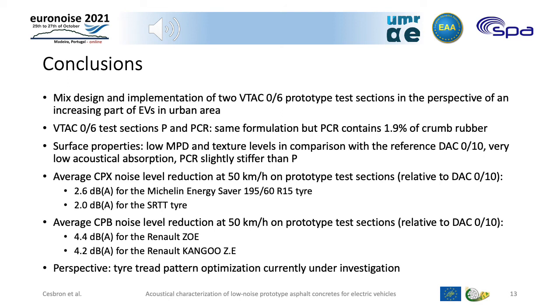A very low acoustical absorption was measured on both prototype test sections. Regarding the mechanical impedance, the PCR test section was slightly stiffer than the test section P. In terms of noise performance, the average CPX noise level reduction at 50 kph on the prototype test sections was 2.6 dBA for the Michelin Energy Saver tires and 2 dBA for the SRTT tires. The average CPB noise level reduction at 50 kph on the prototype test sections was 4.4 dBA for the Renault Zoe and 4.2 dBA for the Renault Kangoo ZE.